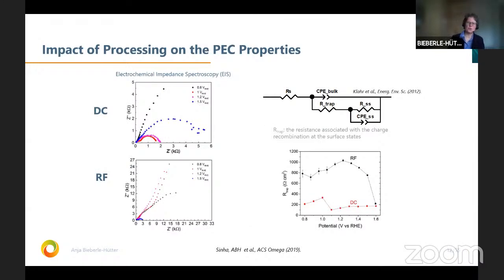And then when we go to the photoelectrochemical properties, we see here the impedance data. We see that we have different performances, which is related actually straightforward from what we see in the current density data. And for this study, we fitted this to equivalent circuits like they are shown in the literature, and shortly to see that this is the resistance associated with the charge recombination at so-called surface states. We have here also the semicircle for the surface states, bulk capacitance. And here in this plot, we show that indeed for RF sputtered, we have a higher R-trap resistance.